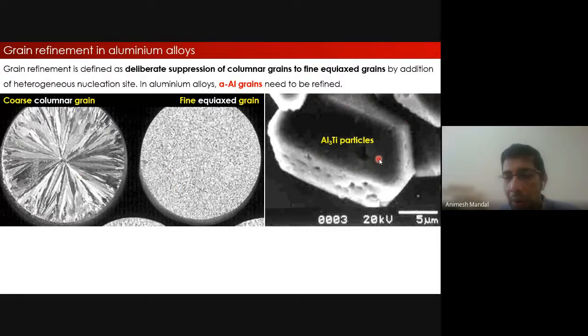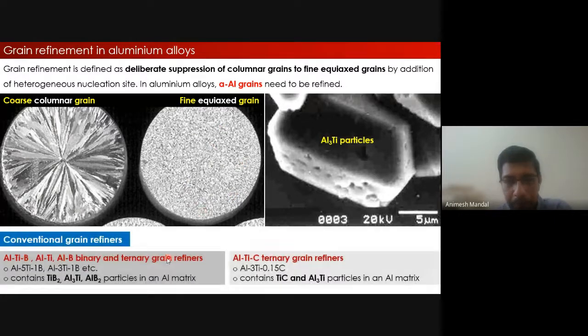Al3Ti particles. Then there are certain particles like titanium diboride. They are very commonly added so that these particles act as substrates for nucleation of alpha aluminum grains, and thereby you generate a fine-grained material, which is expected. Now there are many kinds of grain refiners which are added. Traditionally you have aluminum titanium boron alloys, aluminum titanium alloys, and aluminum boron alloys. All these binary and ternary alloys are added.